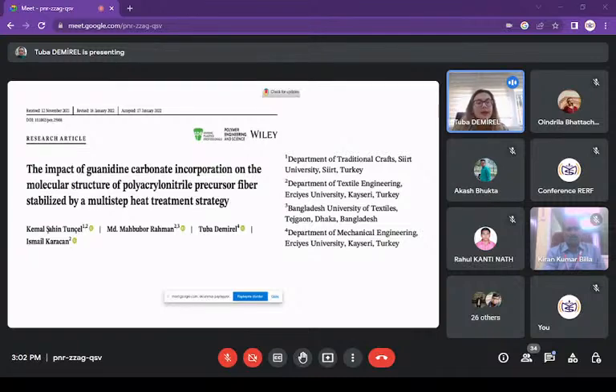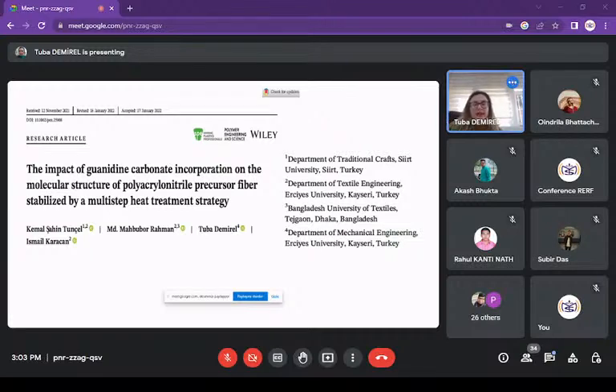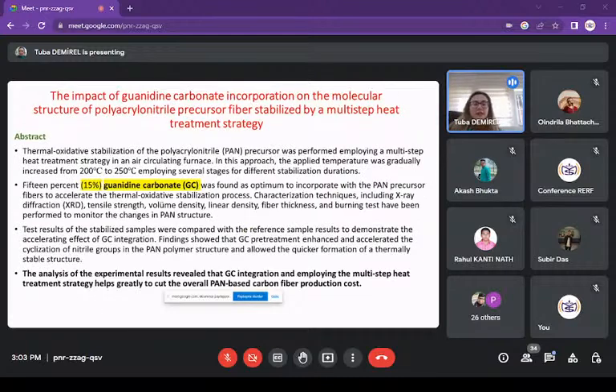Another article is on the impact of guanidine carbonate incorporation. In this article we use guanidine carbonate. The guanidine carbonate at 15% was the optimum incorporation in the precursor fibers as an accelerator, and I use the same analyses as the other two articles. The characterization technique is very important.